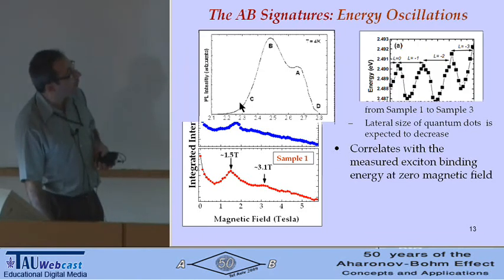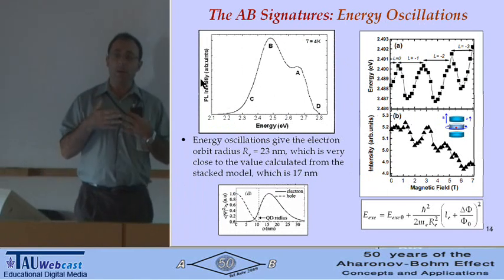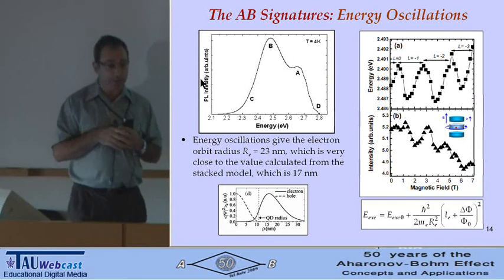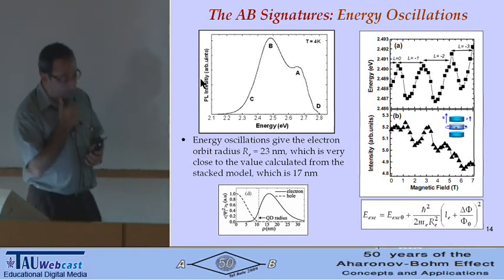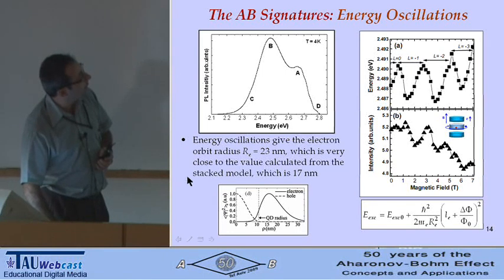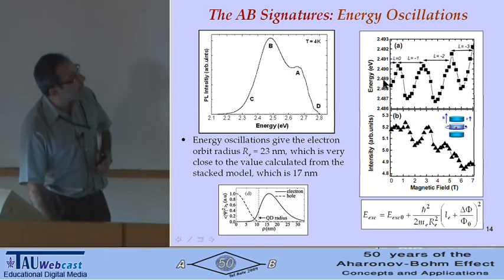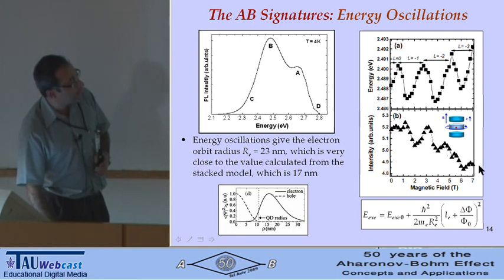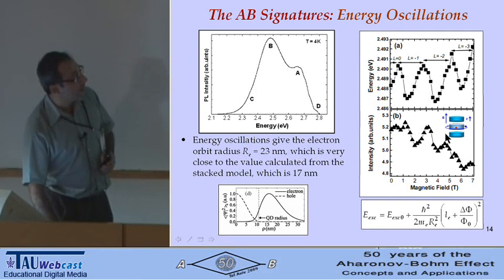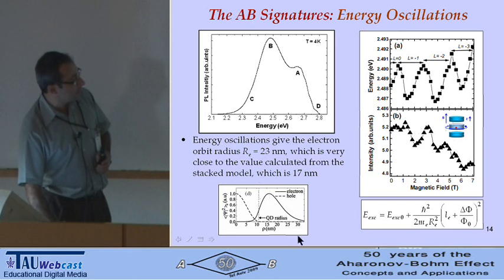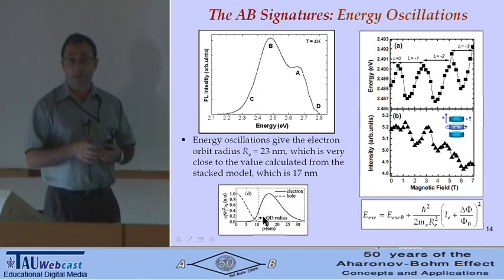So that's intensity oscillation. Now we had to do a slightly different experiment with a focused laser beam, and it was done on the same samples at University of Buffalo. We had to do more precise measurements and fit the curve. If you do that, you can really resolve a very nice energy oscillation of the exciton, and at the same time you can see oscillation in emission intensity. If we calculate the radius of the orbit from this oscillation, we get about 23 nanometers. And from the stacked model I mentioned, we estimated about 17 nanometers for the radius of the electron. So that allows you to measure the quantum dot radius.